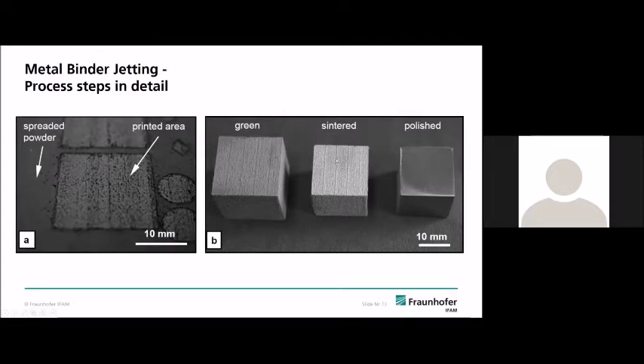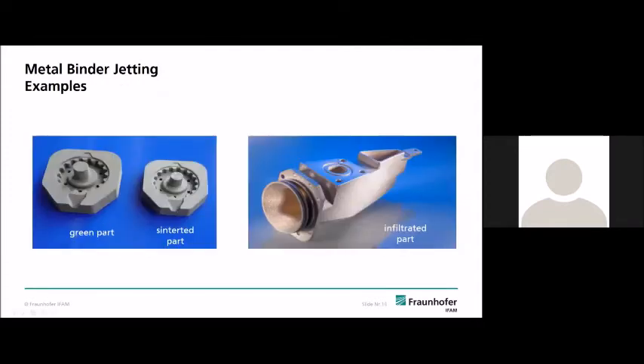You have the sintered part, which is smaller due to the shrinkage during sintering, and you can polish the part. Here again, comparison of green part and smaller sintered part. And the part displayed here on the right is an infiltrated part, where you have only pre-sintered, almost no shrinkage, and you infiltrate the part with a lower melting material like a bronze, for example. The matrix may be a steel material, and the bronze is then the lower melting material for the infiltration.